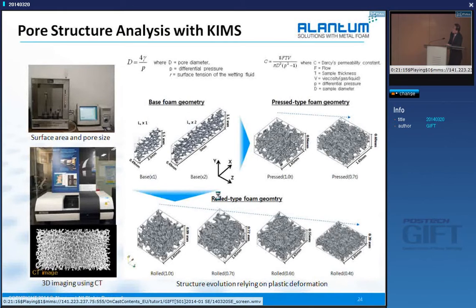The leader of this KIMS project is Dr. Yun Jung-yeol. And what we are doing is, again, we have a size limitation of a pore. The bottom is, I mentioned, the 450 microns, right? If we want to make smaller or finer pores, there's no way at this moment, because polyurethane foam has a kind of limit of the pore size. So in order to produce more fine pores, we are doing two ways.